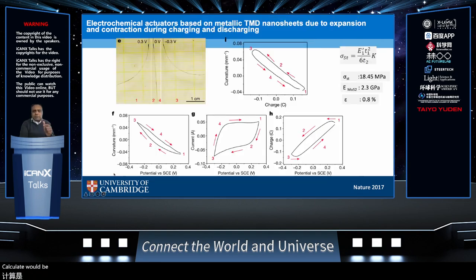This is quite interesting because it allowed us to then calculate the physical properties of the restacked films. By applying positive voltage and negative voltage, we were able to make the cantilever actuate in the positive and negative direction. And the change in curvature is directly correlated to the CV characteristics, and that is the intercalation and deintercalation of ions leads to this actuation in both directions. And so one can do lots of different measurements with different thicknesses of MoS2 and on different substrates. And by fitting that data, we can extract the Young's modulus of these restacked MoS2 films, which comes out to around 2.3 gigapascals. And the strain capability of these actuators is on the order of 0.8%.